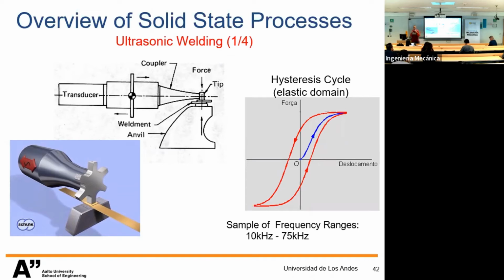Classic mechanics is essentially a basic formalization of our mechanics knowledge, and elastic deformation also doesn't exist. Elastic deformation is based on the exploration of the metallic bonding between different particles, so you change the distance between them, but you always violate some of the most extreme distances between the components. So each electron belongs to several nuclei of atoms of the metal, that is the metallic bonding. But some are more extensive, and you always break some of that metallic bonding. So it's never totally decoupled. So we take advantage of not being totally decoupled, where with 20-25 kilohertz of cycles per second of alternating compression and tension, we generate some plastic deformation. Plastic deformation means that you generate new chemically active surfaces. This process of plastic deformation generates heat, and you have then the heat and the compression force.